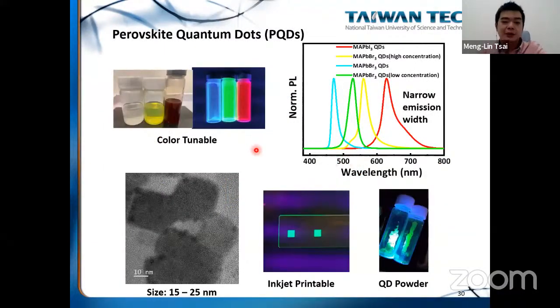So here is what we are studying in our group. We use perovskite. We try to synthesize chemically dispersed perovskite quantum dots in different solutions, and we evaluate the PL behavior of the quantum dots. We characterize the size, and we try to come up with inkjet-printable inks. This is very useful if you want to replace the traditional color filter with these quantum dot color conversion filters.